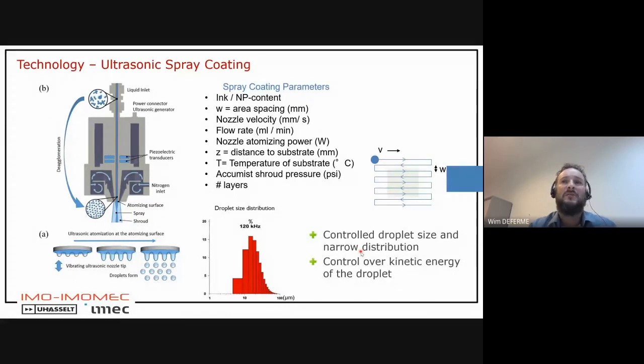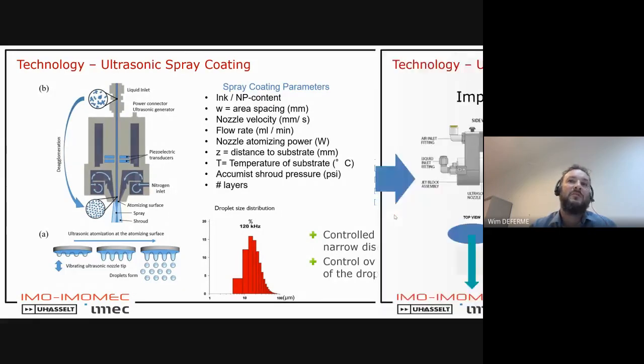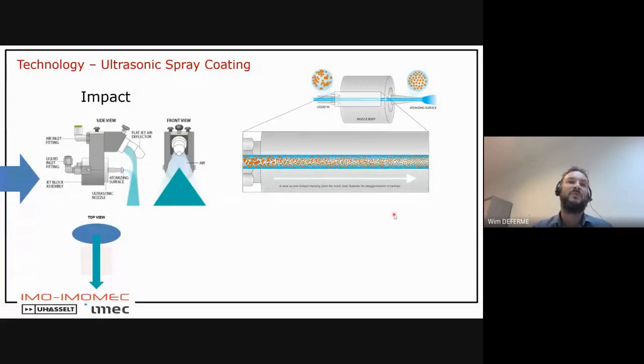We have several nozzles. You can have nozzles where you really make a pattern, and you start, like you see on the right side here, coating over a very small area. In principle, we have the opportunity to go to line widths in the order of 100 micrometers. But of course, you talk about ultrasonic spray coating. So if you want to go to large area coatings, you can go for what we call the impact nozzle. And this impact nozzle can really spray one substrate up to 30 centimeters in width in one track. And that's just by changing, let's say, the nozzle geometry.